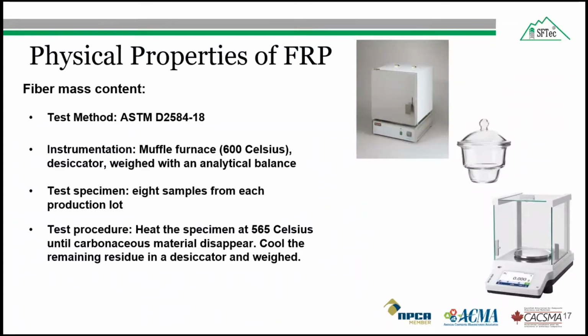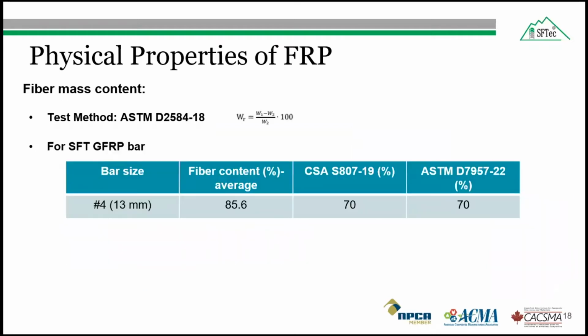So the fiber content by weight percentage was calculated using the following equation, where W1 is the weight of the specimen and W2 is the weight of the residue in gram. So for example, for the SFTec glass fiber reinforced polymer bar number 4, the average fiber content was found to be 85.6%, and which was higher than the 70% requirement in both CSA S807 and ASTM D7957.